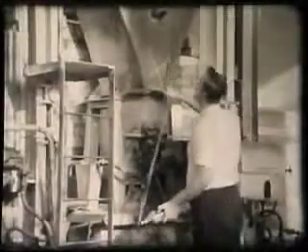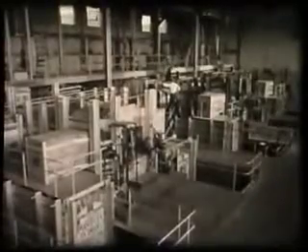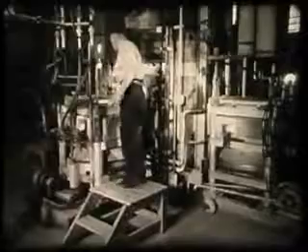An automatic device gradually feeds the raw materials into the tank, which is heated to approximately 1400 degrees centigrade. Each furnace runs night and day for many months and only stops when a tank needs to be rebuilt. At the other end of the huge tanks, the glass is drawn off in the form of tubes of various sizes, an internal current of air keeping the molten glass in tubular form and controlling its diameter. As it ascends, external air streams cool it and control the thickness of the wall.